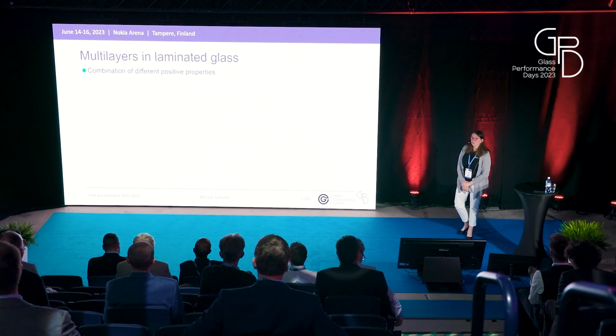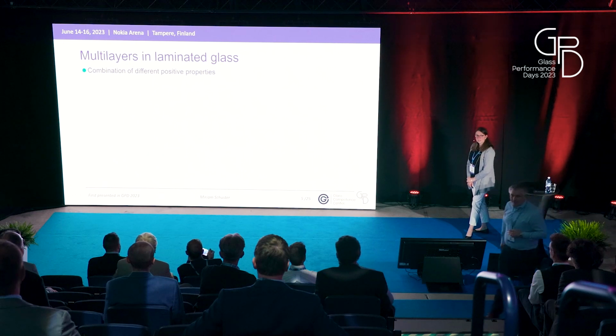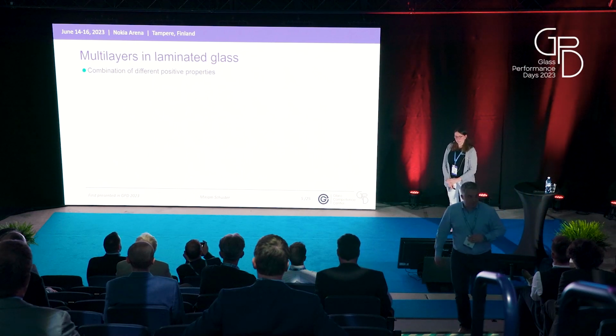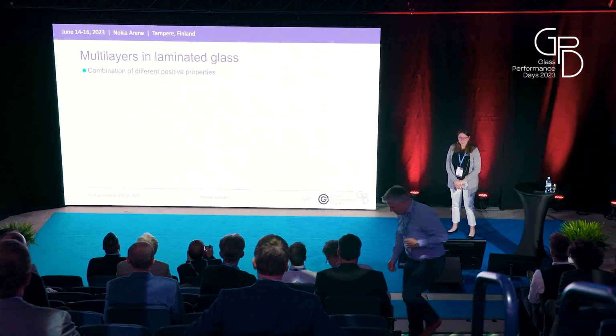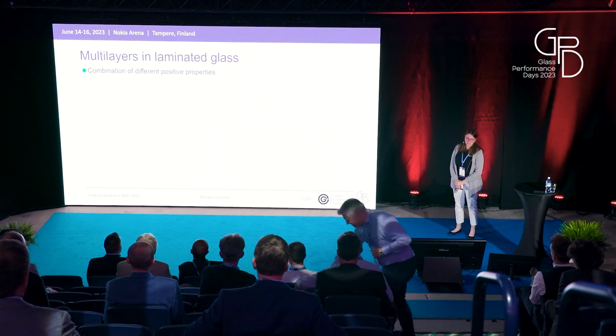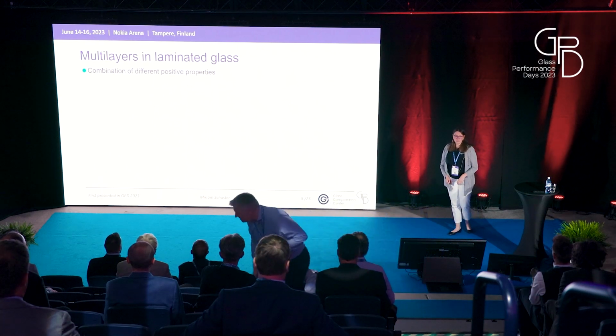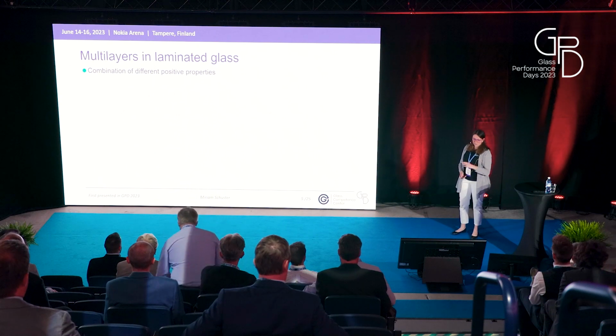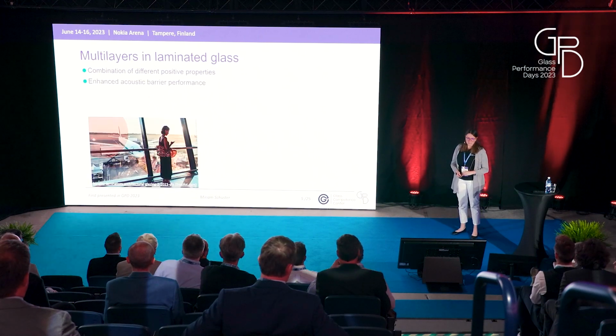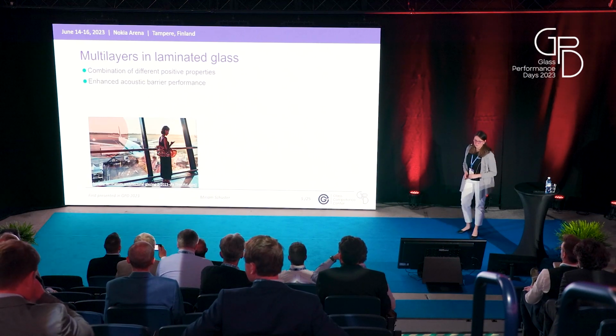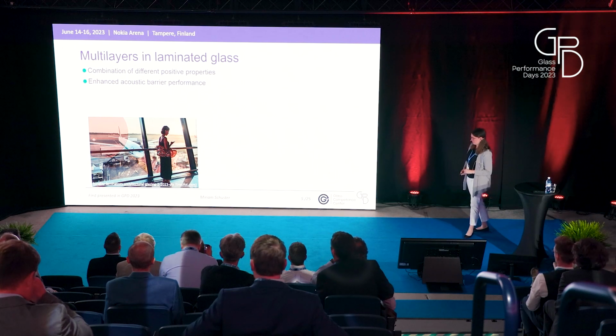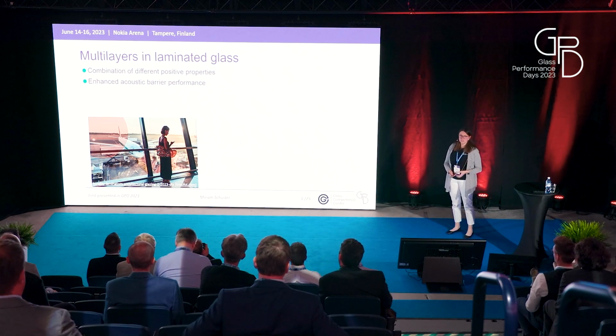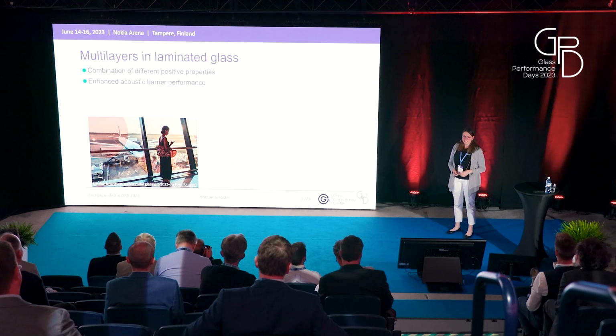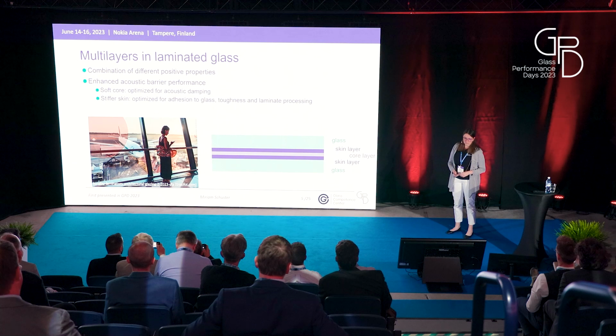So why do we use multilayers? By using different layers or materials as interlayers, we can combine the different positive properties. One example in laminated glass in the architectural context is acoustic barrier performance, as we see, for example, in this picture. In order to have a good acoustic performance, we need a high damping. And high damping is achieved with very soft interlayers.